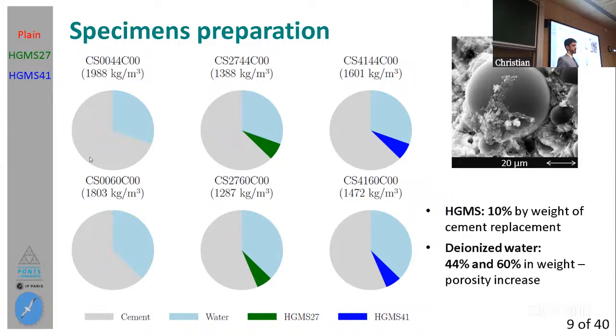And then you will see that we have these 2 other columns of specimens. The first one is where we replace partially, 10% in weight, cement by spheres. That's why the name goes with 27 there. And the last one is 41 because we have done the same, but with microsphere 41. Then we have obviously the same water to solid ratio. It is worth noting the differences that we already obtain in terms of density, where we go from 2,000 kilograms per cubic meter to around 1,400 kilograms per cubic meter. So we had an important decrease in density, which is important in the context of lightweight materials. And we did that also changing the water to solid ratio.